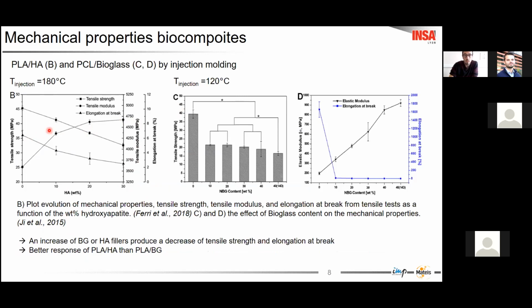In the literature, they also studied the mechanical behavior of two kinds of biocomposites, PLA with hydroxyapatite and PCL with bioglass. I will present two examples where the samples were elaborated with the same process, injection molding. In these two studies, they observed the evolution of mechanical properties, tensile strength, elongation at break, and modulus, as a function of filler content.